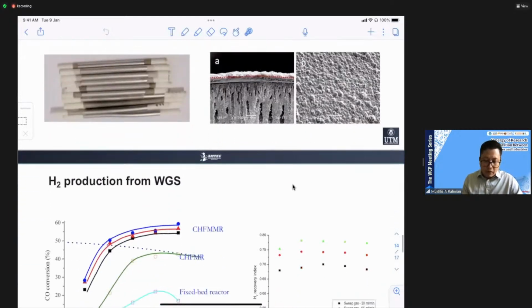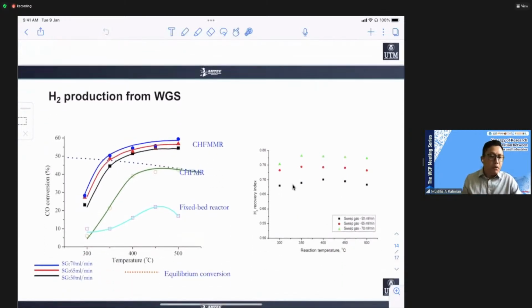So we performed the water gas shift reaction using the palladium membrane. You can see that we compare once again the catalytic hollow fiber microreactor, without the presence of the membrane, with the fixed bed reactor. You can see that the water gas shift reaction in here managed to reach the equilibrium conversion. The water gas shift reaction is an exothermic reaction, so you can't have conversion beyond this line. But we proved that compared to the fixed bed, our ceramic hollow fiber microreactor is better.